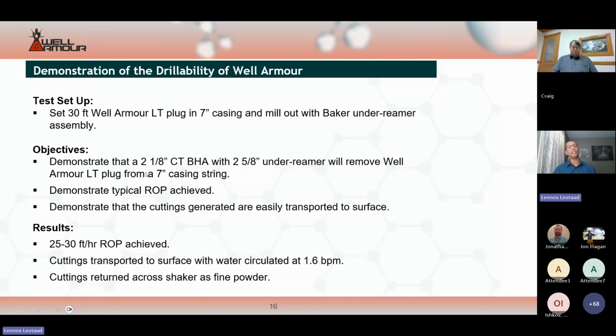Some drillability testing, and this is just provided here as an example. We've already done jobs and have been able to drill out Well Armour successfully without any issues. But initially a small scale test was done where Well Armour was placed in 7-inch casing and a Baker underreamer assembly was used to drill it out. For that test, an ROP of 25 to 30 feet per hour was achieved, and just using water circulated at 1.6 barrels per minute, we were able to transport the cuttings and get them out of the test setup.